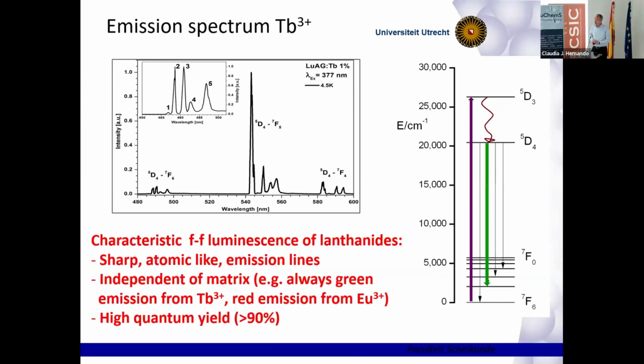Now, if you look at the luminescence, the emission spectrum of terbium, it's shown here. And that is quite unique. If you excite in the UV from the ground state, because normally terbium is in the ground state, but we excite with UV photons that are resonant with the transition from the ground state to the 5d3 in the UV, the terbium is excited to the 5d3 level. Then it relaxes by giving off some energy in vibrations, heat, to the 5d4 level. And then the gap to the next lower level is so large that from the 5d4 level, the terbium returns to the ground state by emitting light. And it does that in a very special way.